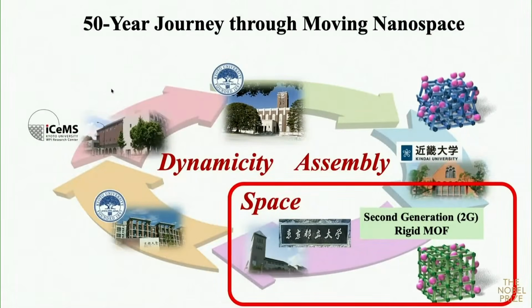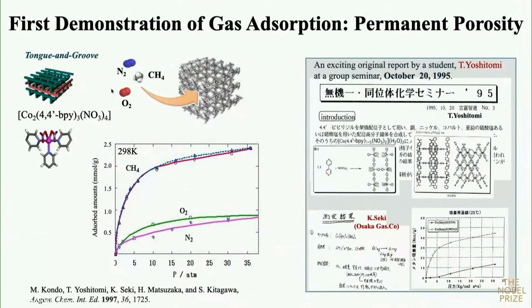So I moved on to Tokyo Metropolitan University. Instead of copper-1, we used the cobalt-2 plus ion to construct this kind of network structure. Without guest, this structure maintained the pore. So we carried out gas absorption. We succeeded very well in this case. But this is a very exciting original report by my student, Mr. Yoshitomi, at the group seminar, October 20, 1995. He showed this crystal structure, and in addition, Dr. Kenji Seki, a collaborator at Osaka Gas Corporation, measured gas absorption, and he sent us the raw data by fax. This is the data, okay? So it was very exciting at that time.